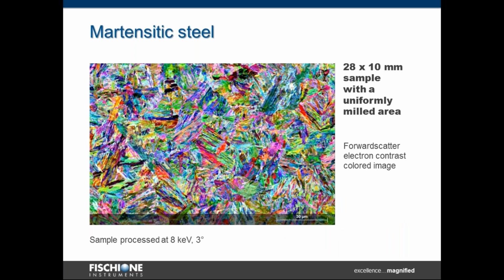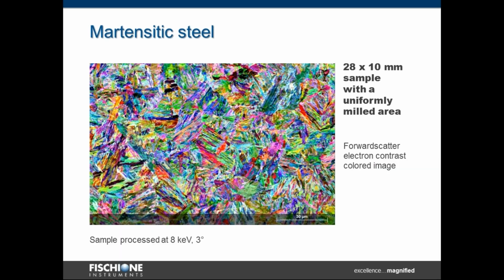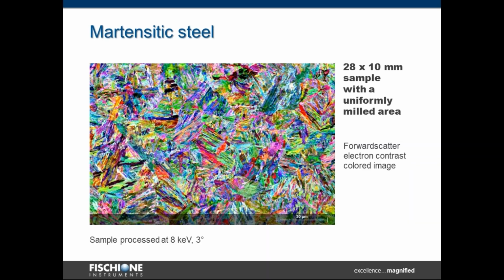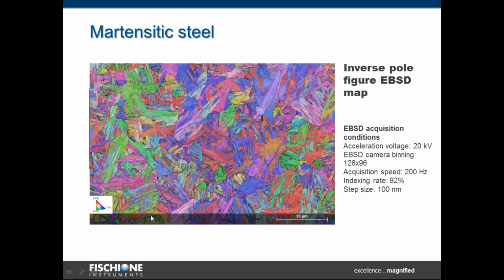Another example is martensitic steel. Here you see the martensite sample, with dimensions of 28 by 10 millimeters. As you can see, the forward scatter electron image shows very sharp crystallographic contrast, with lots of martensite, and it also shows that the surface topography after ion milling is very shallow, which is very important if you want to get such beautiful images. Another slide shows the corresponding EBSD map, acquired at quite high speed and quite high binning.